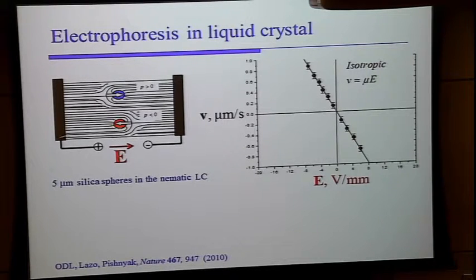And so we are also dealing with a geometry in which the director is already parallel to the electric field everywhere. And so we are not that worried about dielectric Frederiks-like relaxation or reorientation of the director. Moreover, in most of the experiments, we are using liquid crystals that are specially designed with delta epsilon being 0. So there is no dielectric torque on the material. So, and then we repeat the same observation.